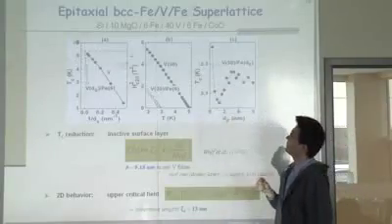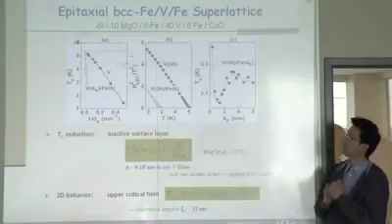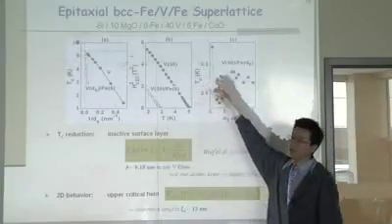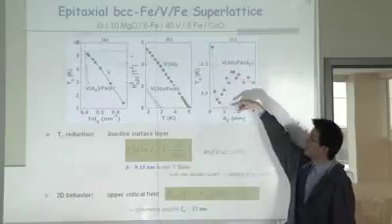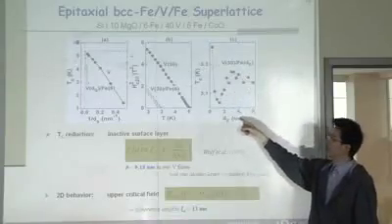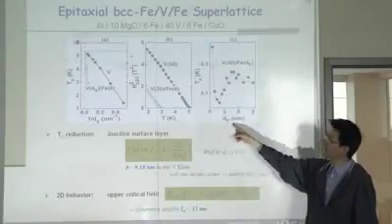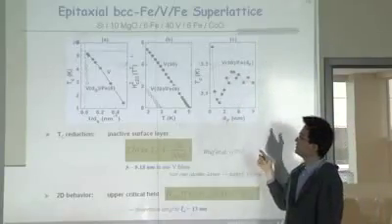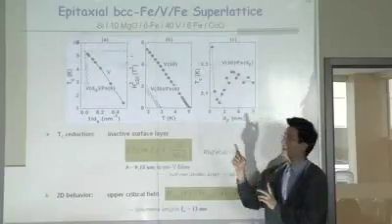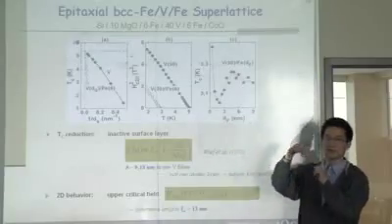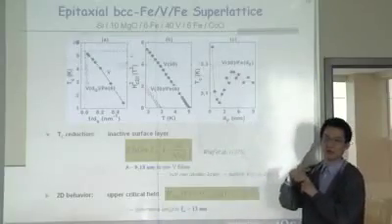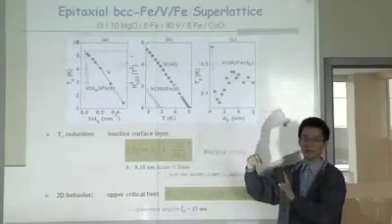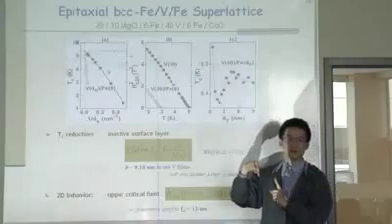The third piece of information is a little bit hard to understand. You see that the transition temperature of the system is a non-monotonic, oscillating function of the ferromagnetic layer thickness, the iron layer thickness. The reason is that when the Cooper pairs enter the ferromagnetic material, they feel a very strong exchange interaction. One of the electrons will be accelerated, the other one will be slowed down.